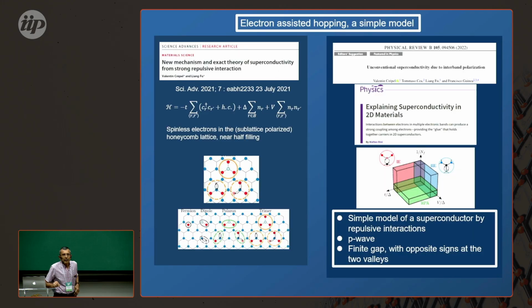But okay, I would like now to turn to superconductivity, and before that I want to show you what is probably the simplest superconductor you can cook up based on repulsive interactions. That was invented by Valentin Crépel and Liang Fu like 3 or 4 years ago, and it's based on the honeycomb lattice. You have spinless electrons, you have only nearest neighbor interactions, so you cannot have an on-site Hubbard term. And then you have a strong sublattice potential, and you're near half filling, so basically one of the two sublattices is full or almost full, and then there are extra electrons or extra holes.